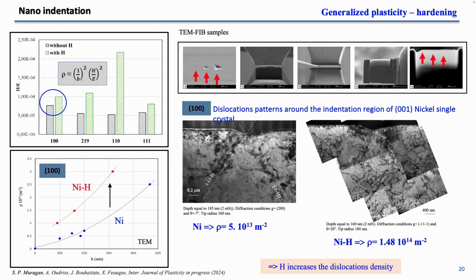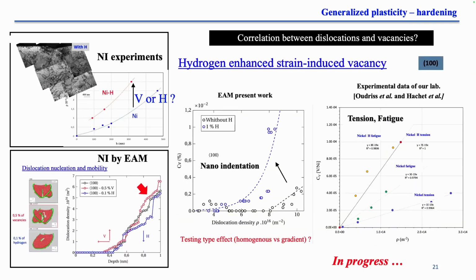And to check that, we prepared FIB samples and observed the dislocation density near the tip and show that we have a large increase of density of dislocation when we add hydrogen. It's the result of this curve. This is depth, and the density of dislocation as a function of the depth of the indent. With nickel and with nickel with hydrogen. And we can conclude with the effect also of a vacancy. This increase of the density of dislocation with added hydrogen can be linked to the vacancy or hydrogen or both.